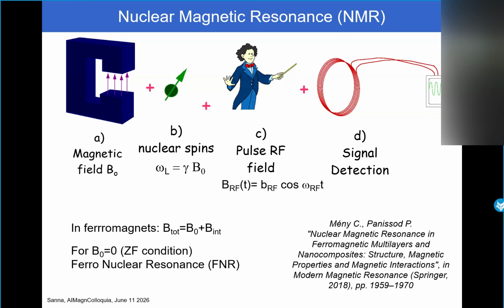Now, by using a radio frequency, by simply using a coil perpendicular to the applied magnetic field, we can turn this magnetization from the z-axis. Typically we want the magnetization to be on the xy plane where the coil is.